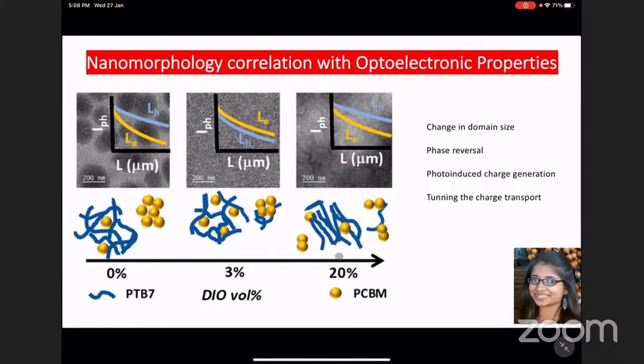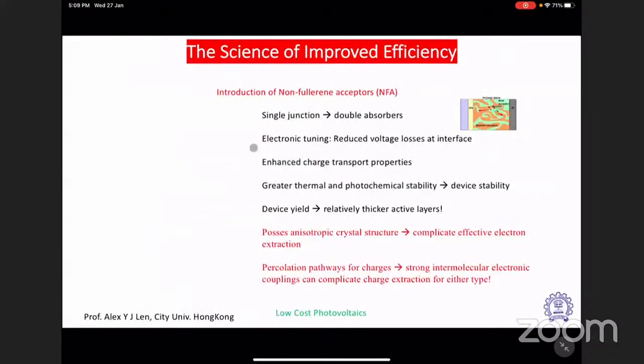So by adding this kind of solvent additives, we can indeed tune the morphology, and we can go for the optimal morphology, which is at 3%, to get the equal charge transport length scales for both the systems, which is required for more optimal efficiency of the solar cells.